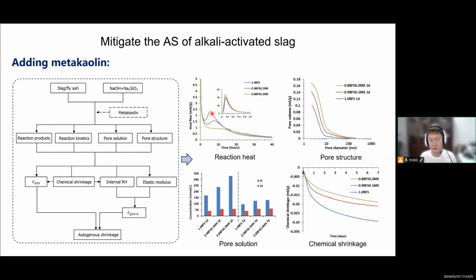So for example, the reaction rate is reduced a lot. Actually, this phenomenon is very similar to a higher modulus of activator. If you use more silicate in your activator, you will find a similar phenomenon here. So the reaction rate is reduced in this part, and the pore structure is coarsened, which means a lower capillary pressure when you have metakaolin.